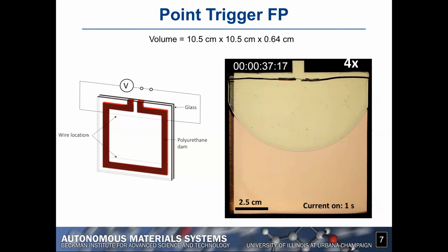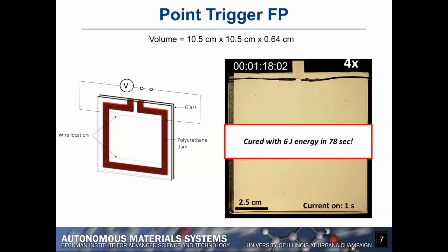So ahead of the front, we have a very liquid monomer. Behind the front, we have a fully polymerized solid that would have the stiffness of about 3 gigapascal, which is typical for polymer systems. And the idea is that we can actually make this with about 6 joules of energy in about 78 seconds, which is substantially less than what it would take if we were to use a bulk polymerization in, let's say, an autoclave type of system.